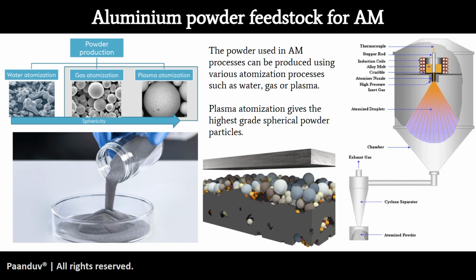The second option is ball milling, the good old ball milling, but in that case, the sphericity of your powder particles is quite bad, and hence the amount of defects that you can see during 3D printing can be quite huge. So you can see on the image on the top left here that water atomization gives you the worst sphericity, followed by gas atomization, and then plasma atomization really gives you very high grade spherical powder particles.